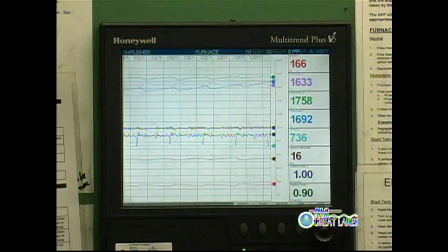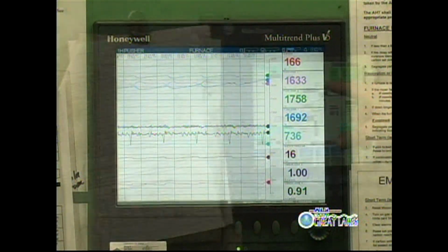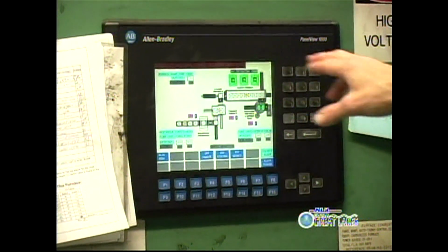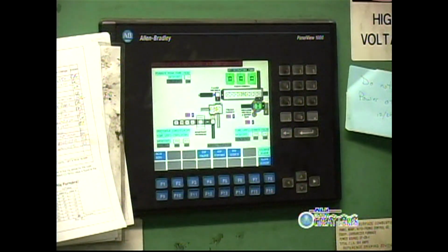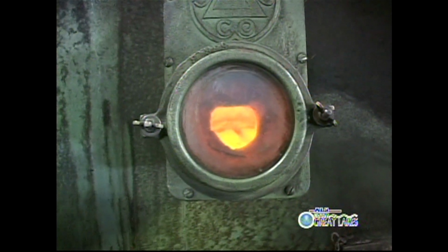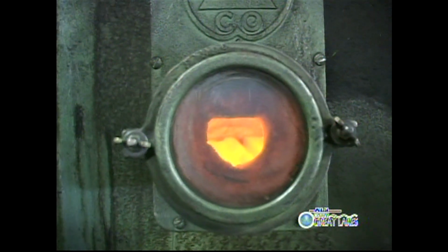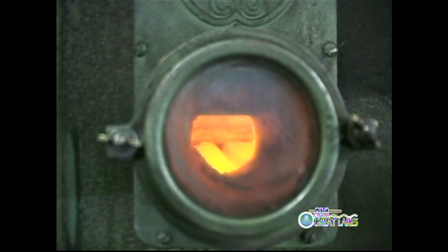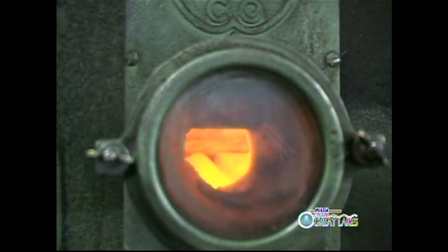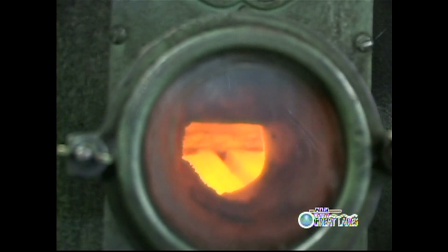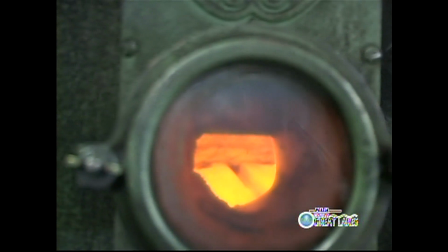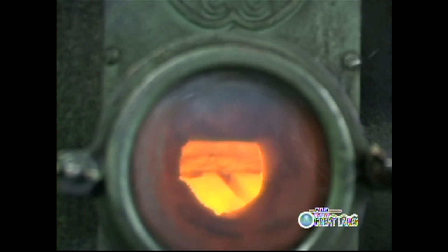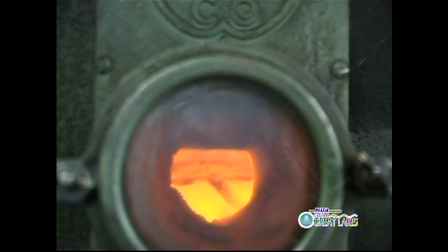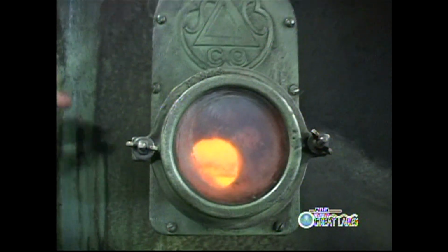As you can see, we control the process, monitor and check it every hour: temperature, carbon, oil temperature, part tracker, that tracks parts through the furnace. What you're looking at is through a side glass, of the last zone in this P9 pusher. That's 1,550 degrees. A load will travel down there, and when it comes time, that inner door will open, and this giant pusher here will push this load into the quench.